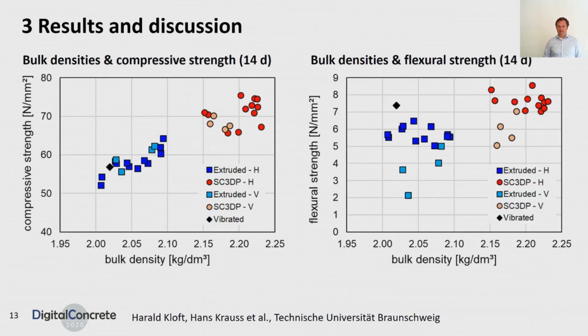This is different for the flexural strength results here on the right diagram as compared to the compressive strength results I showed before. First, we can see a generally different level of strength, with the highest strength for the shotcrete 3D printed specimens and the lowest strength for the extruded specimens as compared to the vibrated specimens. And second, we can clearly see a detrimental effect of the main interface and maybe also of delay time. We have not resolved the delay time in this diagram, but